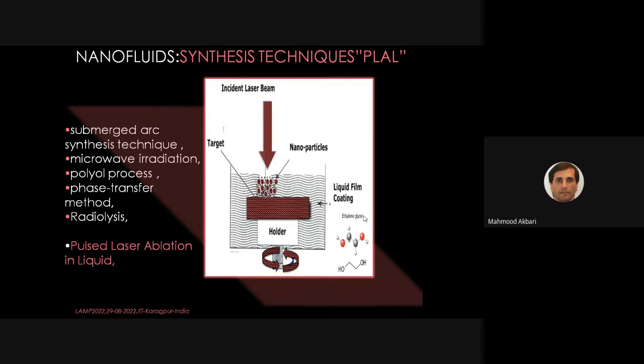It consists of having a target covered with the host fluid within which we would like to have our nanoparticles, and we come with the laser and ablate that material, that target. We use a rotating target to ensure that we are not ablating at the same position, to get a better size distribution, and so that the absorption coefficient will be somehow homogeneous within the target itself.